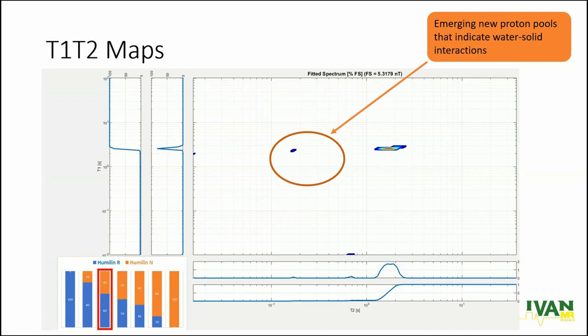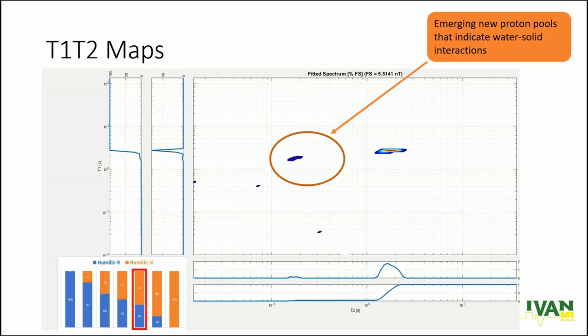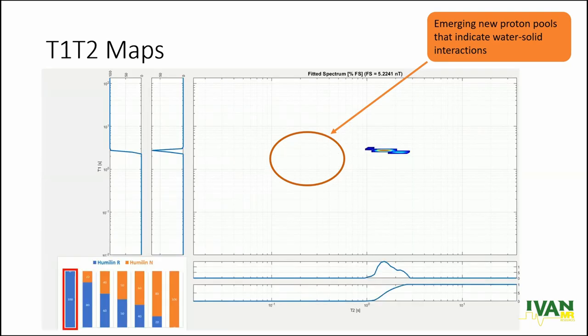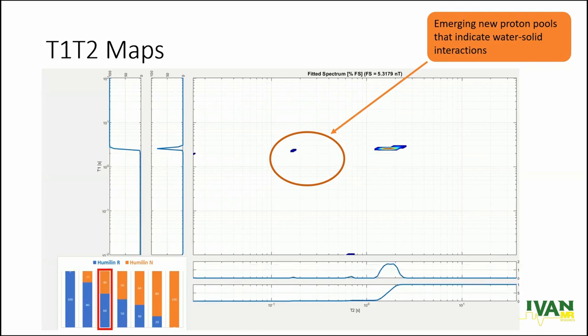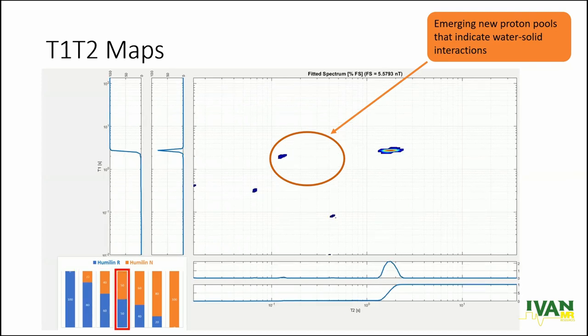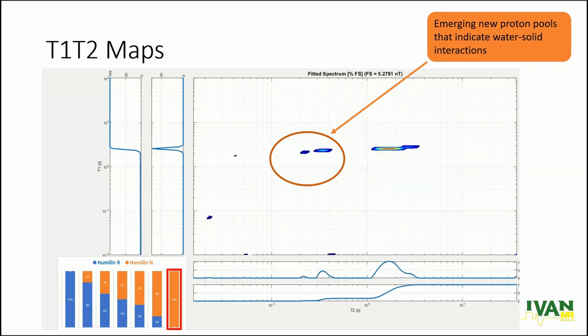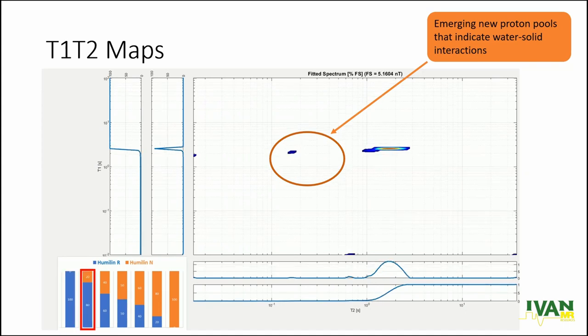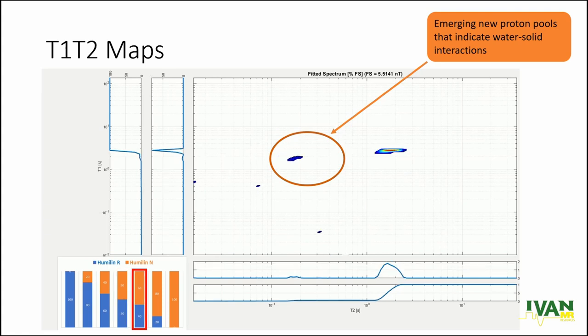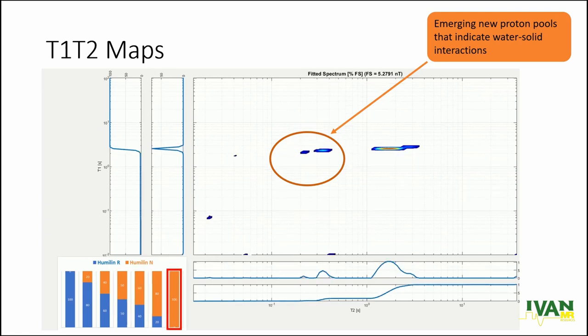With each increase in the Humulin N, the intensity of the proton pool in this area increases. This area indicates the water-solid interaction of the undissolved part of Humulin N. So as it is a suspension, in the circle you can see that the area in proton pools is increasing with increasing Humulin N concentration in solution.